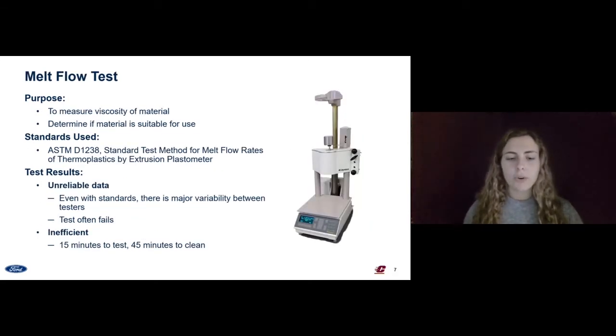The second test performed by Ford AMC is the melt flow test, and this is our main area of concern. This method uses a heated barrel to melt the specimen into a viscous fluid, and then the material is forced out by a piston. The data collected determines viscosity, and analysis of that determines if thermal degradation has occurred.